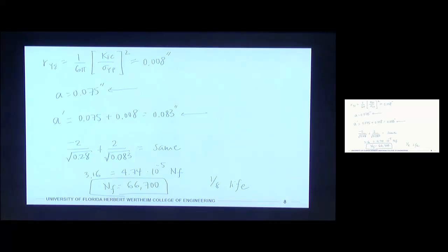And so if there is a plastic zone there, we can make that correction. And then based on the other questions from prior, we could make this a little bit more accurate by taking into consideration how the maximum stress is changing as the crack grows, and then also how that C1 is changing as the crack grows. And so does that kind of make sense? Yeah? Okay.